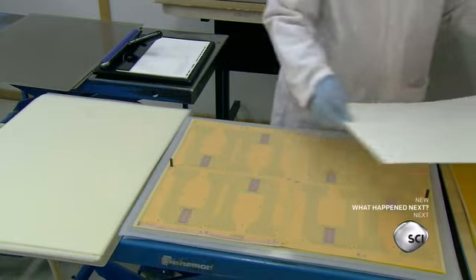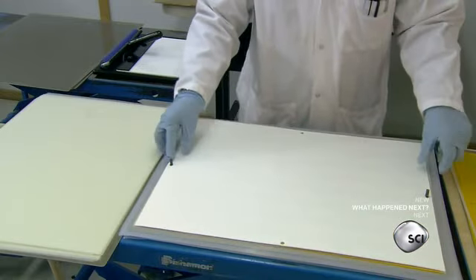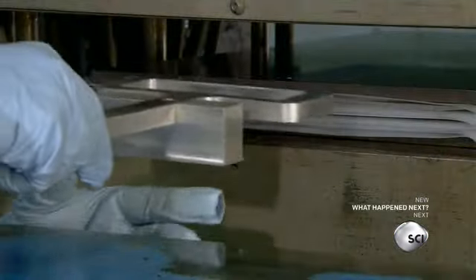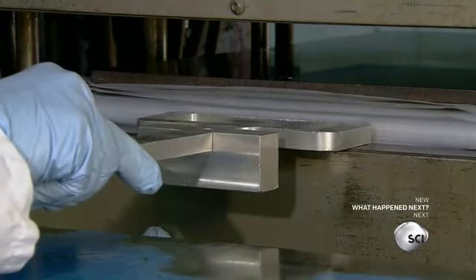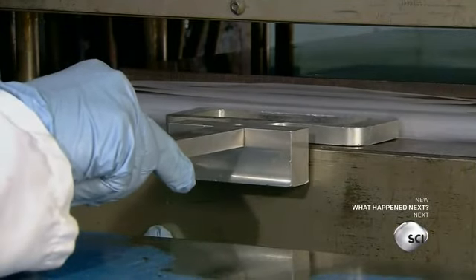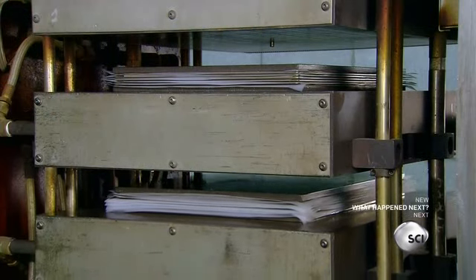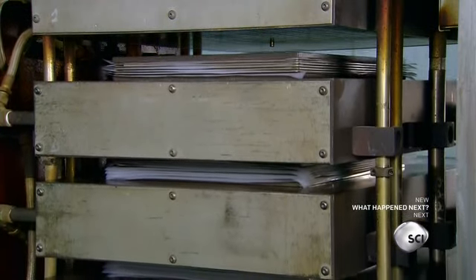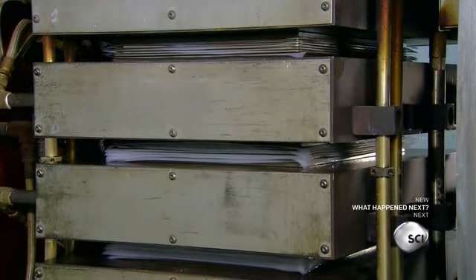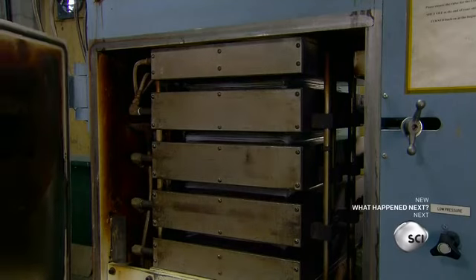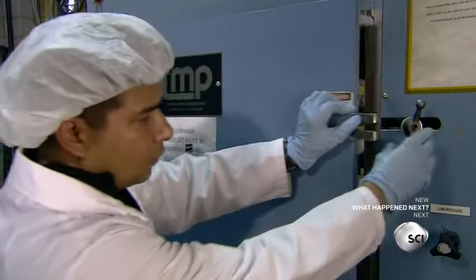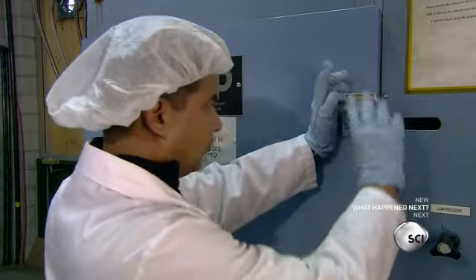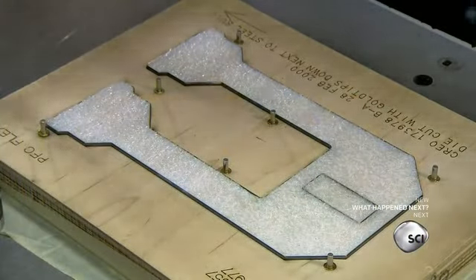As it forces the insulation film deep down onto the panel, it encapsulates the circuitry. They load the panels into the lamination press, apply a vacuum to remove the air between the layers, and start her up. For the next hour and a half, the press simultaneously applies high pressure while heating the panels to 400 degrees Fahrenheit. When the panels cool and come out of the press,